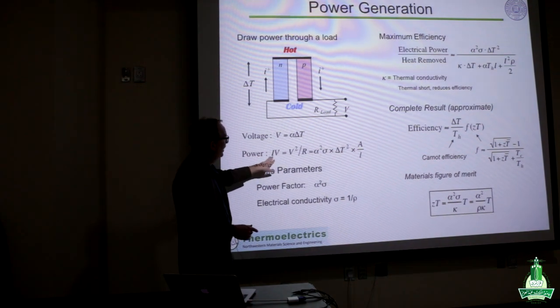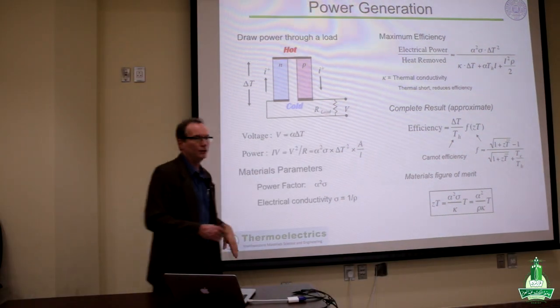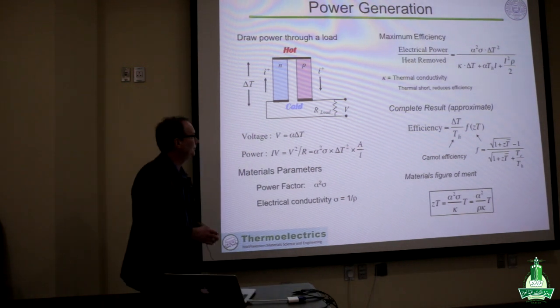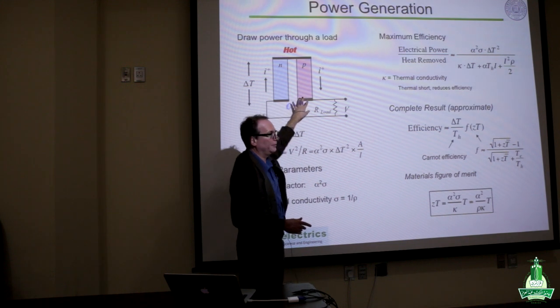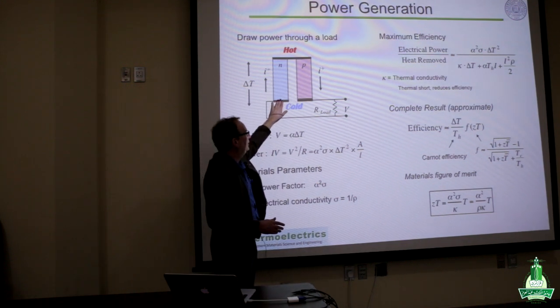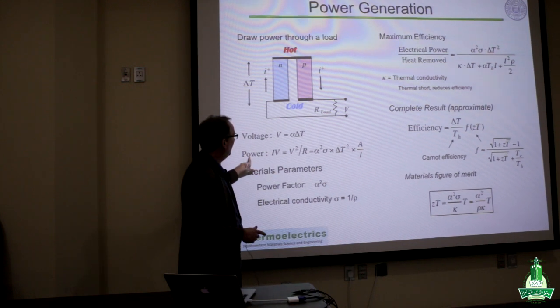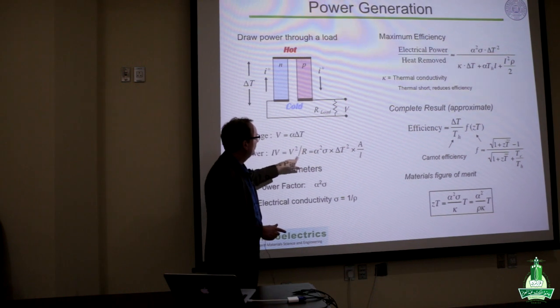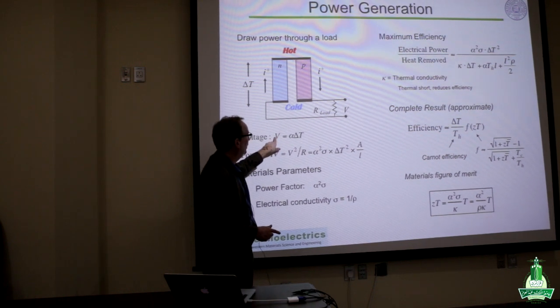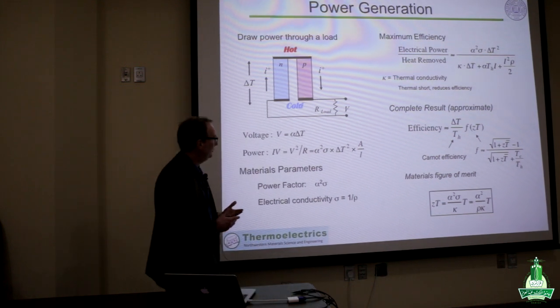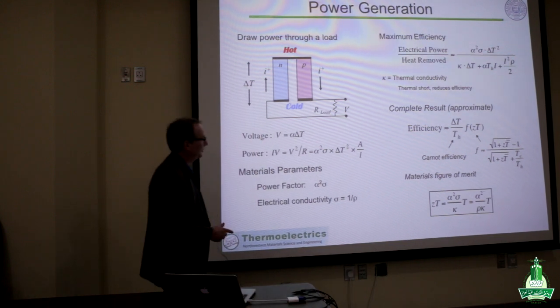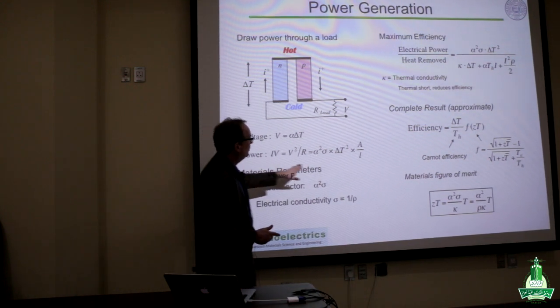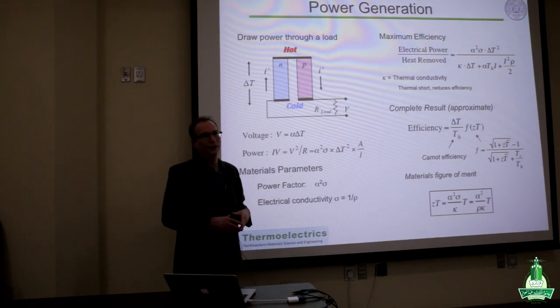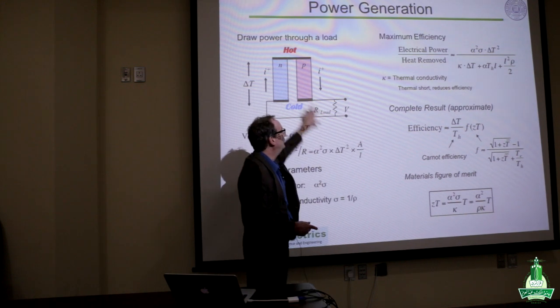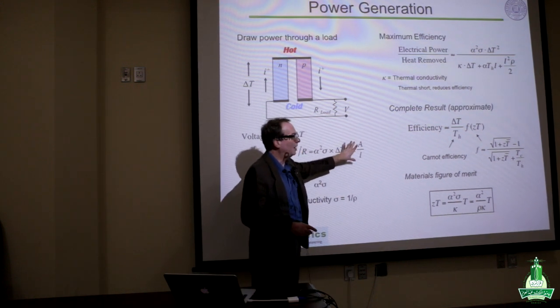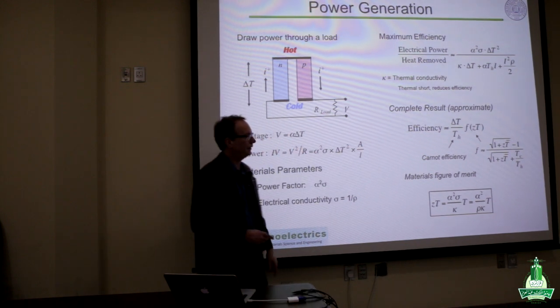So mathematically, we know that current times voltage is V squared over R, where R is the resistance of the circuit. And in this case, we're limited by the resistance of our thermoelectric material. So that means that our power from our device is proportional to the Seebeck coefficient squared from the V squared, but also now the electrical conductivity, where electrical conductivity is 1 over the electrical resistivity. And then also for power, we're going to have terms that depend on the outside parameters, such as the temperature difference across our device and the geometry of the device, the cross-sectional area and length of the device as well.